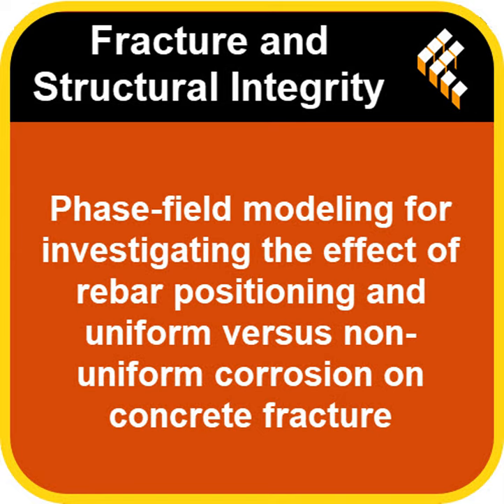Did that change the crack patterns much? Interestingly, no. The overall pattern of cracks, those corner-directed and edge-parallel ones, didn't change drastically compared to the non-porous case for either uniform or non-uniform corrosion. But did it affect the rust levels? Yes. The structure with the pores consistently showed larger rust expansion displacements needed at both T1 and T2. So it took more rust to cause the same kind of cracking if pores were present?